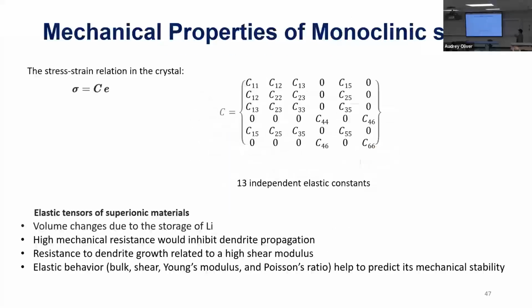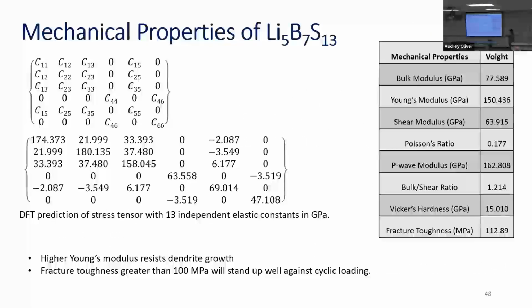Then we also look into mechanical properties based on the crystal structure. We know how many independent elastic constants there will be. We can compute all of them, and after that, we can calculate all the mechanical properties: bulk modulus, Young's modulus, Poisson ratio, and so on. Why mechanical properties? In those materials, lithium insertion and extraction happens. In the electrolyte and also the anode, volume expansion and contraction happens. That will degrade the material.